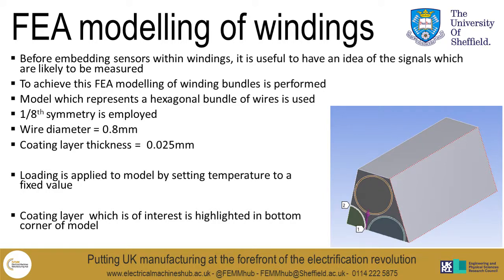So in addition to the temperature in the windings, another parameter that's of interest is the stress that's on the insulation layers of the winding. To study this, we've built the FE model, which can be shown in this slide. It uses 1/8 symmetry, and the wires are 0.8mm in diameter. The coating layer on the conductors is 0.025mm. To apply a thermal stress to the model, we apply a fixed temperature to all the elements within it. And the coating that we're interested in is the one which is in the middle of the bundle, which is highlighted in the bottom left of the model.